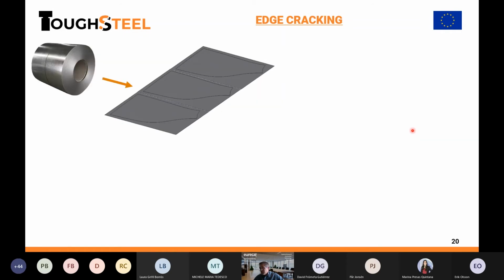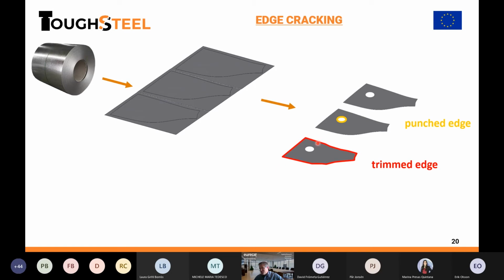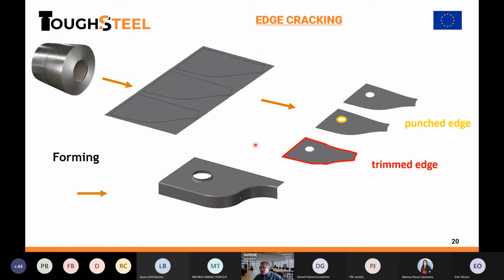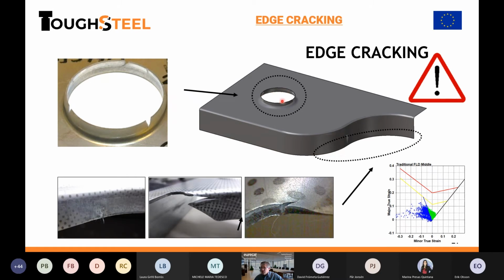Let's go for that. But this is not working, because to build this component, we start from a steel coil. We cut it in parts, and for that we separate it, we trim the edge. We also make a hole in the center, punch. So these are affected parts. After that, we form it, we bend it. And what was happening here? These areas undergo stretch flanging and hole flanging. And the result is this cracking here in the expanded hole, or cracks in the edge in the flange area. And all of these are, remember, below the FLDs. So this is definitely a problem.